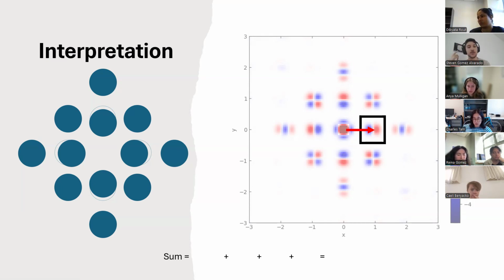In order to interpret our data set, we're going to have to look not just at the vacancy and its nearest neighbors, we're going to have to look at everybody's nearest neighbors. Anytime there's an atom and another atom one unit cell away in the x direction, we have to consider that, because as we saw earlier, all interatomic correlations are going to get superimposed on the same PDF. Okay, so visually, let's see what that looks like.